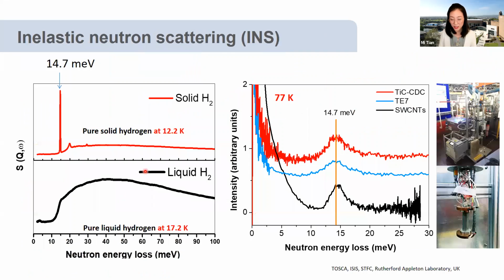This is the inelastic neutron scattering pattern collected on the TOSCA instrument. The experimental procedure is like this. We seal the clean empty sample cell and insert it into the cryostat, and then pressurize it, fill it with hydrogen, and cool down the whole system to 12 Kelvin. Then we know there's solid hydrogen inside the sample cell because we only pump hydrogen in. Then we shine the beam through the cell and collect the data. This is a typical inelastic neutron scattering pattern, and we see a sharp peak at 14.7 meV. That is the characteristic peak for solid hydrogen because we only have pure solid hydrogen inside, nothing else.